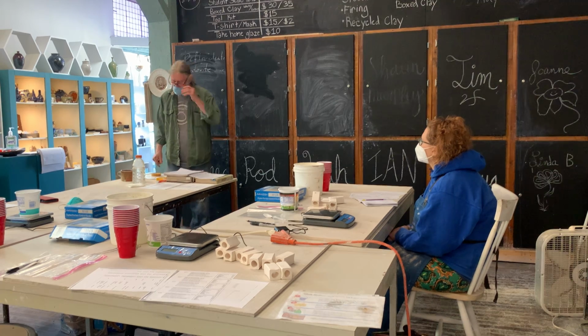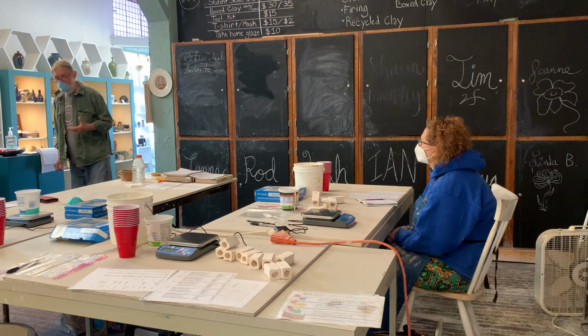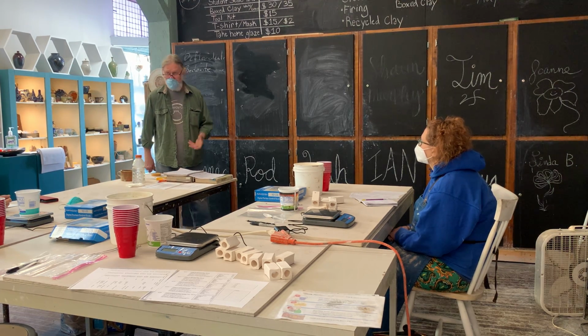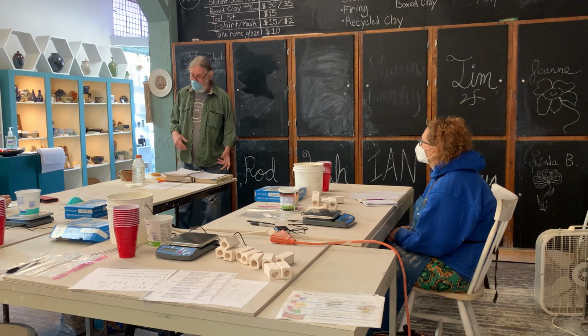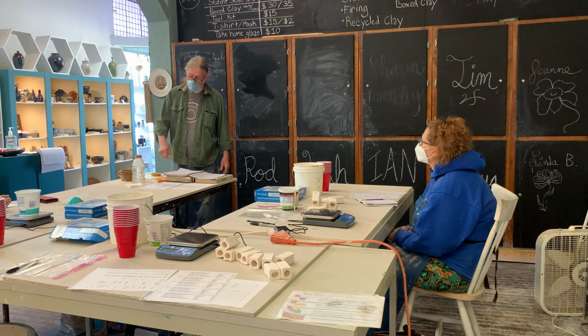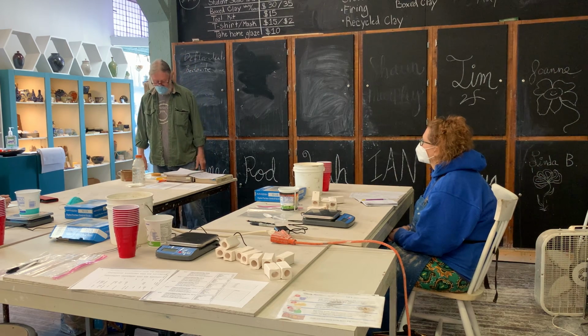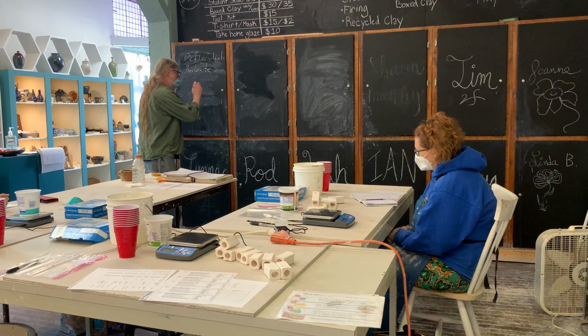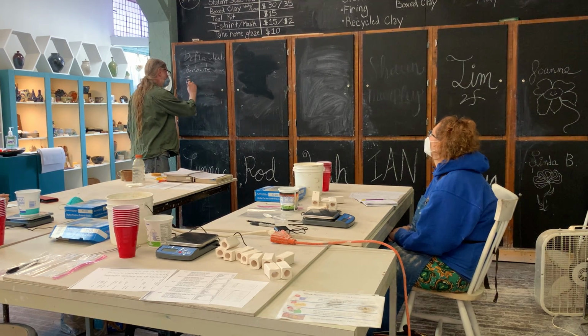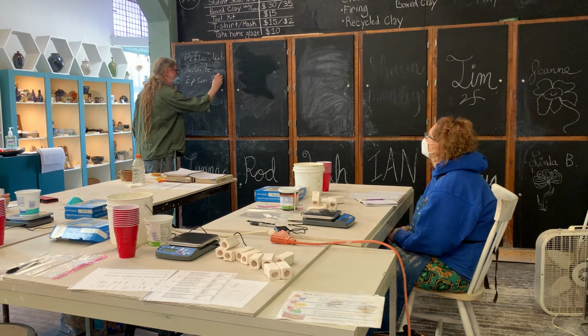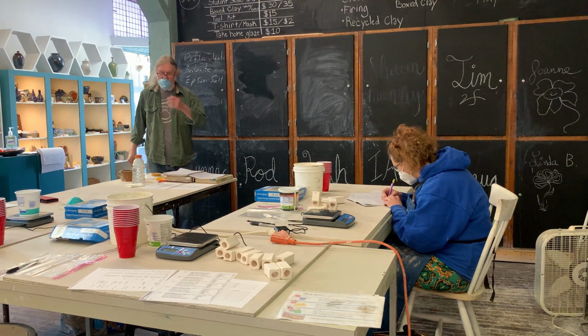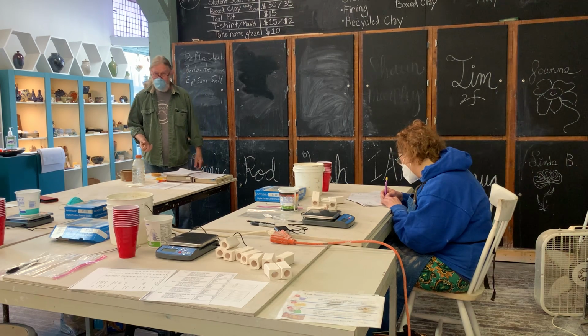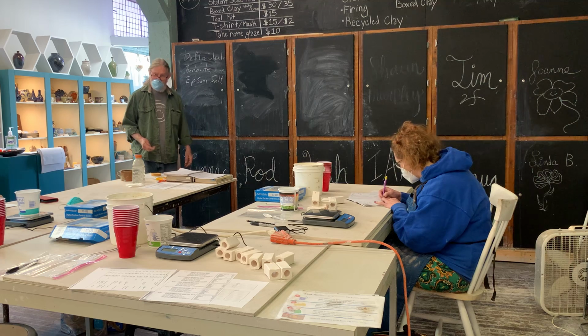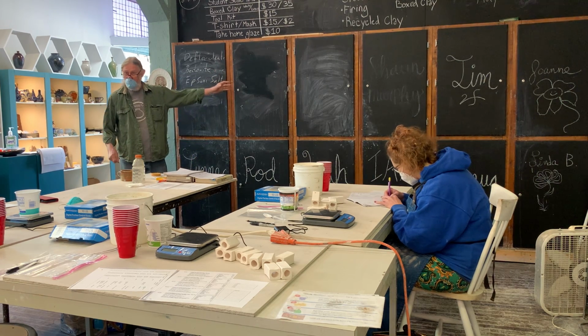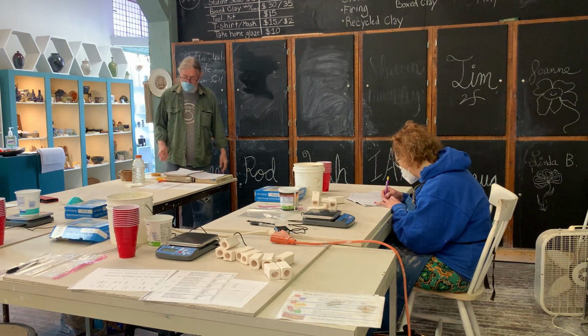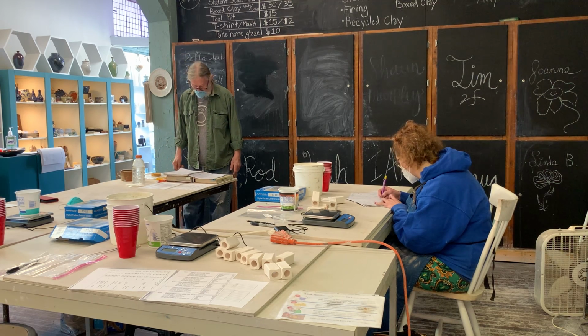Now, there are some glazes, especially those that are fluxed with lithium, that have a tendency to settle in the bottom of the bucket. And I mean settle. If you dump the water out and take some kind of tool and dig into the glaze, you'll find it dry in the middle. If you have that problem, stir about 2 cups of Epsom salt into the bucket. Epsom salt is magnesium sulfate, therefore it doesn't fit into any of the R columns, has no effect on the glaze whatsoever, but it is an electrolyte and will keep that glaze from settling so hard in the bottom.